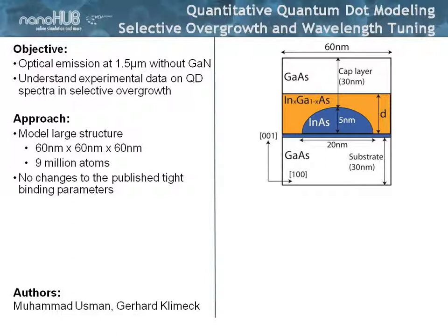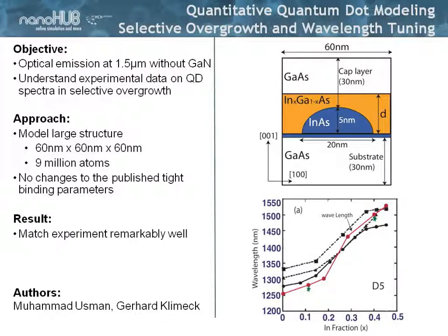There was a set of experimental data available that I will show in a second. What we want to do is model a geometry that is quite extended — 60 by 60 by 60 nanometers — with roughly 9 million atoms in it. What we are trying to explain are the black lines on the bottom right, where each dot on the black line is actually a different device grown by experimentalists with slightly different growth methodologies, showing the optical emission wavelength measured in their experiments as a function of indium fraction in the buffer layer.